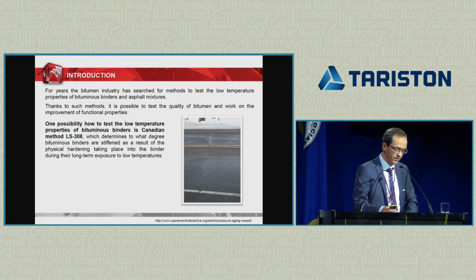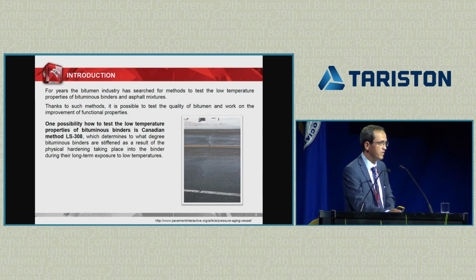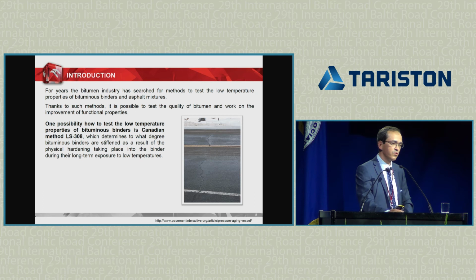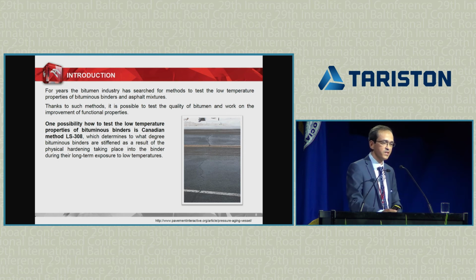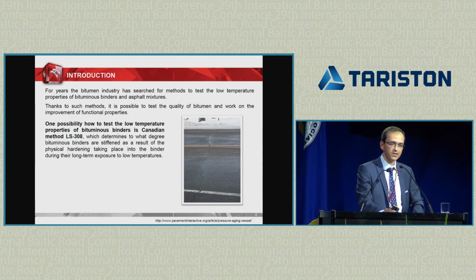Frankly speaking, the bitumen industry for a long time is looking for a method to evaluate not only binders but also asphalt mixtures. And as I said, when we look at rutting resistance, the problem is solved. Everybody knows that in the European standard for rutting resistance there are almost 4 testing methods. But when we think about low temperatures, the situation is not so clear.